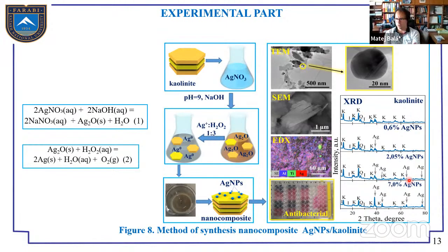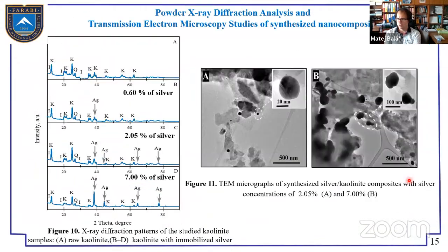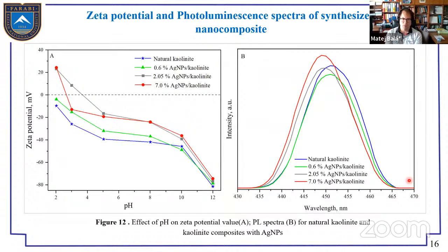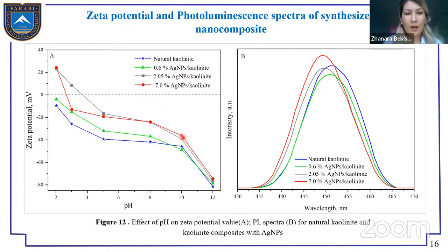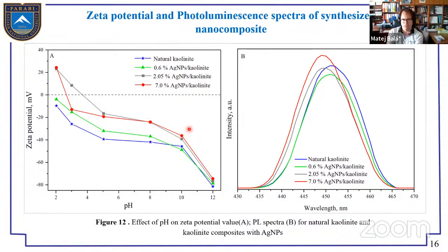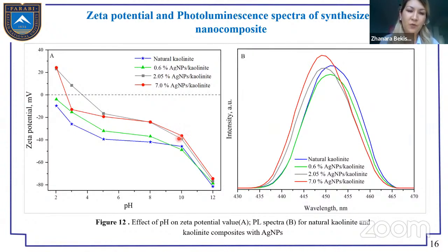Mm-hmm. Okay, then on slide 16, you showed zeta potential results, and there the difference between, for example, the samples containing 2 and 7% of silver is almost nonexistent at pH higher than 6. Do you have any explanation why the results are so similar for these samples? For 7? Yes, the red and this gray curve, why are they so similar? I think it is because of more silver on the surface and the changing of the zeta potential. It depends on when the silver was adsorbed on the support, the potential is changed, and it is more stable when the silver is stable on the support and at optimal pH.